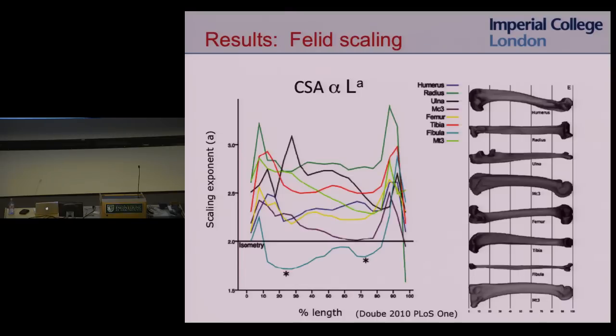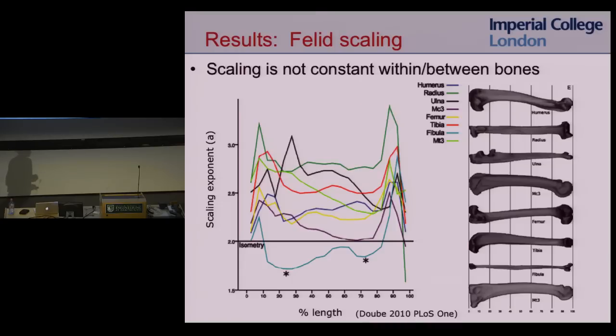So what do we get? This is what we get. So this is plotting the scaling exponent for each bone across the entire length of the bone. Before you get too overwhelmed with this graph, the first thing to notice is that it's not constant. So what's usually reported in the literature is the scaling exponent for the diameter at mid-shaft. And what we notice is that might not be representative of what's going on in the entire bone, particularly at the ends of the bone.